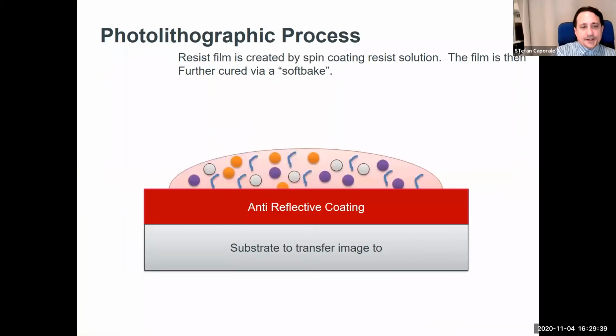So again, let's look at how this process works. This is dispensed onto a wafer. So in a clean room, you have your silicon wafer, you would coat an anti-reflective coating underneath it, and cure that. Again, our solvents here have to not eat away this coating. This is so when your light gets through the film, it doesn't reflect back. And if that happens, you'll actually see the standing wave of that reflection, which is a pretty neat defect to see. But then you just spin this wafer, and you'll spin off essentially all the solvent, and the polymer and all your materials will be left behind.